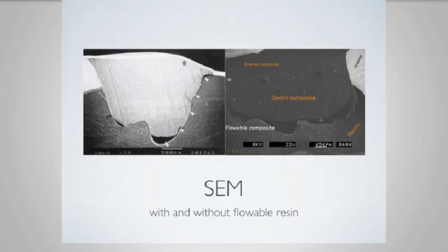If we look at SEM images, just two images side by side, we see that the paste on the left side, without using a flowable resin, has some air pockets there. And on the right side, you see that there's a flowable composite layer between the dentin and the composite, at the adhesive interface. If the paste composite doesn't fully adapt to the surface, it can leave these little pressurized air pockets that create sensitivity to the patient when biting.